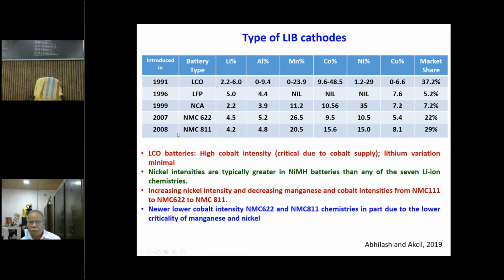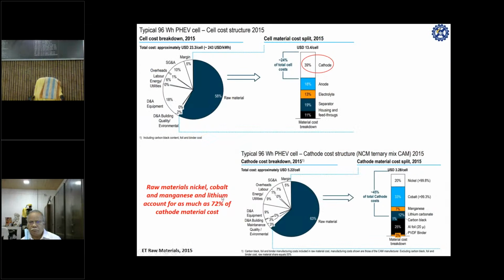But here it shows a very, very good idea that in 2007 post, you have got NMC 622. 622 actually gives you the ratio of nickel, manganese, and cobalt inside it as compared to 811, where you have a lower content of cobalt. And the reason people have shifted from NMC 111 to 811 is that nickel actually helps in increasing charge density, whereas at that time the cost of nickel was very low. But at present, the cost of nickel is very high.